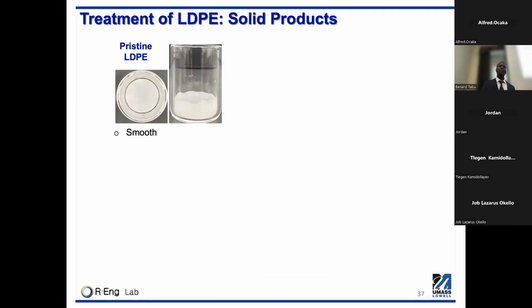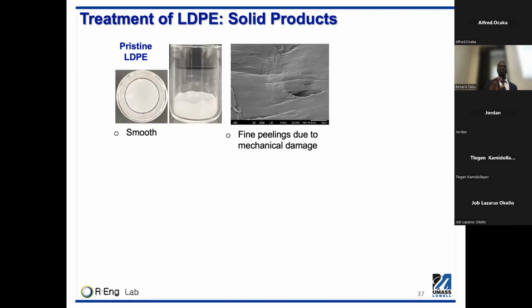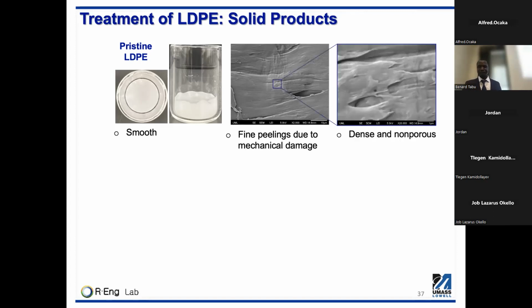And then for the low density polyethylene, it's smooth, as you could see, but on the field emission microscopy under low resolution, the surface is more smooth. It's dense, not porous, but also we see some kind of peeling, and that is attributed to mechanical damage during the sample preparation, because I used the pellet to remove it. And under high magnification, we still see that it's dense and actually less porous.